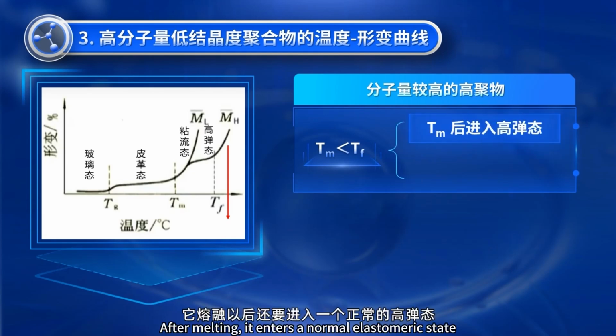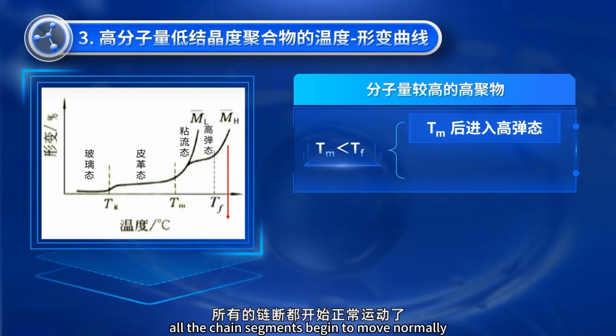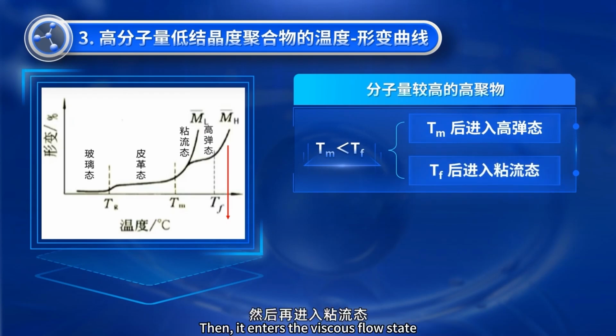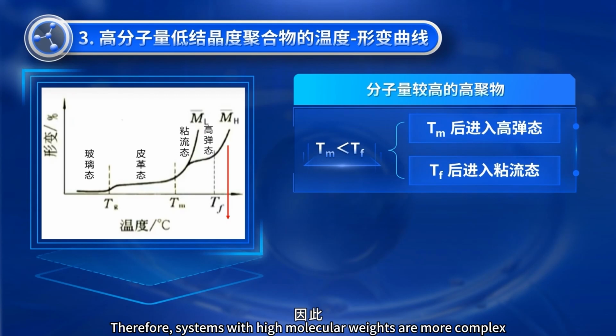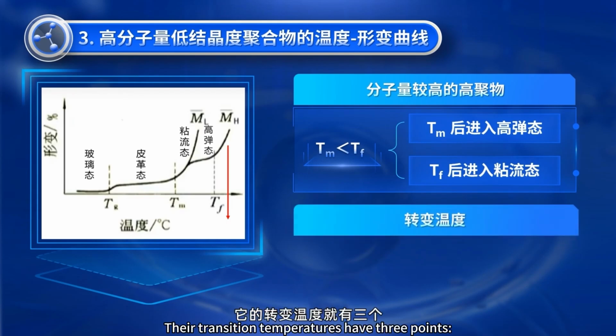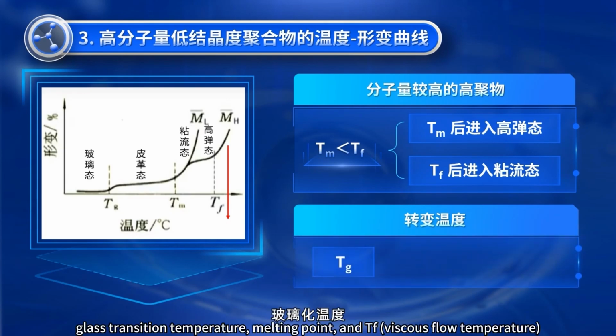After melting, it enters a normal elastomeric state. After melting, all the chain segments begin to move normally. Then, it enters the viscous flow state. Therefore, systems with high molecular weights are more complex. Their transition temperatures have 3 points: glass transition temperature, melting point, and Tf, the viscous flow temperature. At the same time, their states are more varied.